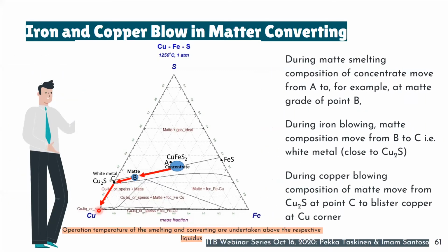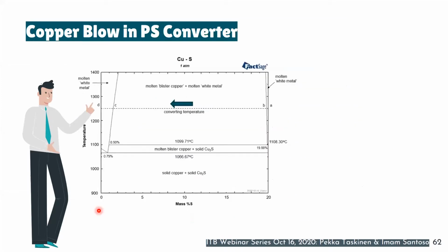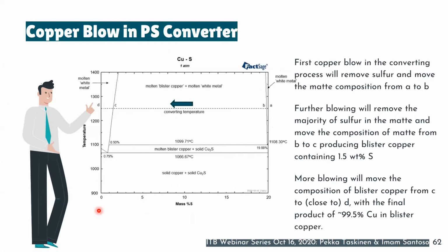So I already described this one, and now this is the copper blowing. In copper blowing, after almost all of the iron is removed, we are now at point C. At this point, we see that the sulfur is around 20% and the copper is around 80%. So during copper blowing, the composition moves from point C to point D. Point D is almost pure copper. So this is basically the process of converting.